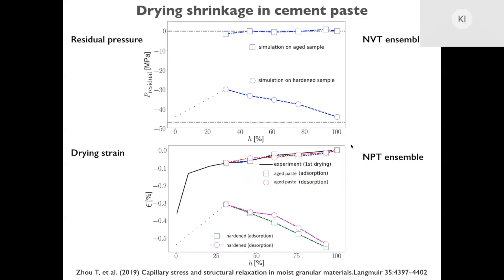So on the bottom figure, you can see the comparison that we have with experiments. So we are able to model the drying shrinkage of cement as a function of the relative humidity. And the experiments are in agreement for what we call the aged paste. So once we have removed eigenstresses from the paste. But we did the same for a paste that had still eigenstresses, so it will be kind of fresh after the cement has been set. And in this case, this is the green and purple lines that you see there.